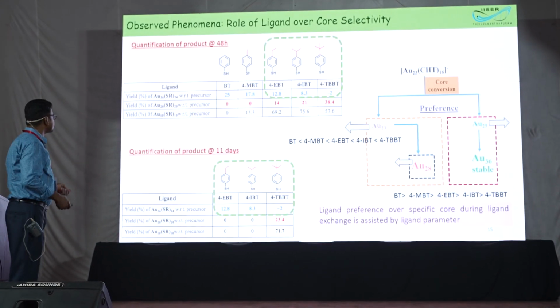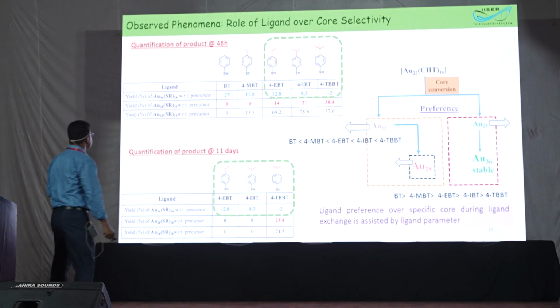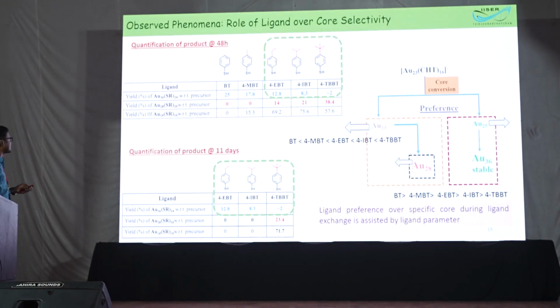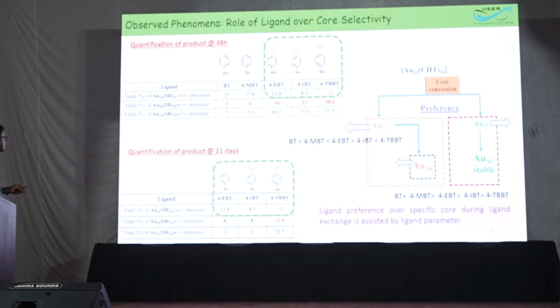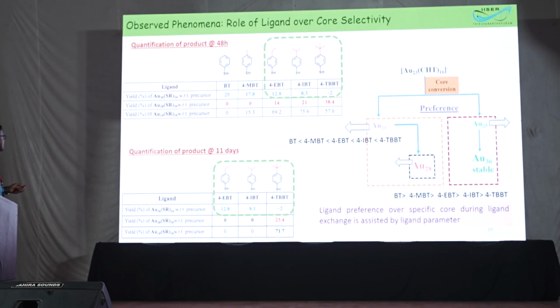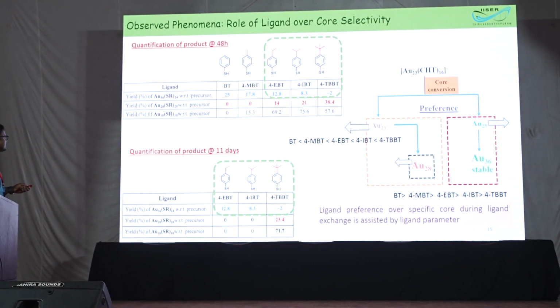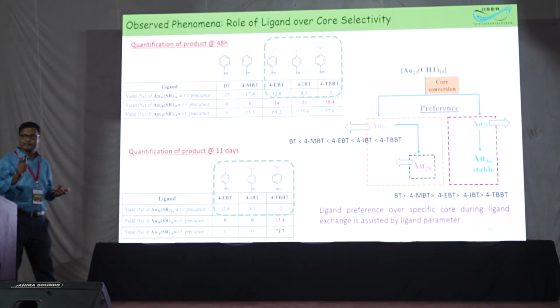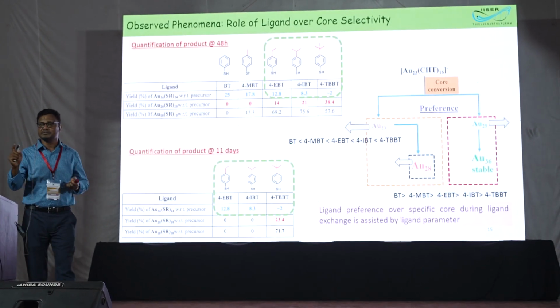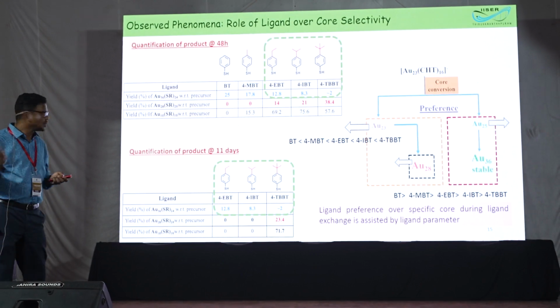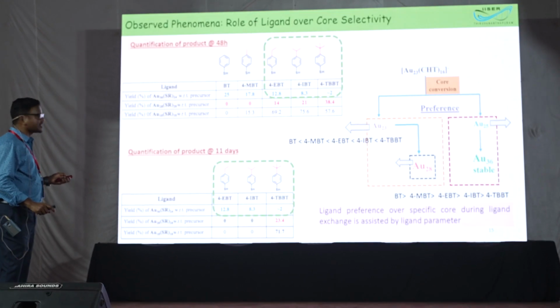Now in each case we can see that when you use benzene thiol, after 48-hour reaction, the yield is quantitative, not qualitative, quantitative yield of the 36 cluster. This is the 28, and this is the precursor. Now the question is that there is a probability that 28 at extreme thermal condition can convert to 36. So can this 28 be converted to 36 or not?